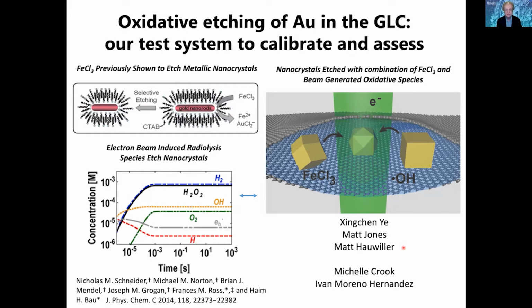So in this case, we will have nanoparticles of different metals, and we will place them inside the liquid cell. And then inside there, we will put a chemical species which can etch the nanocrystal, can remove atoms from it oxidatively in this case. So we're going to have, for example, gold nanocrystals, which when we have iron chloride present, will act to etch a gold nanocrystal.